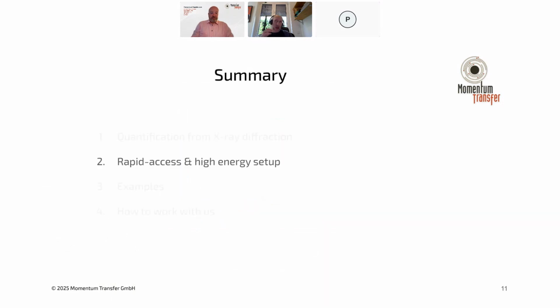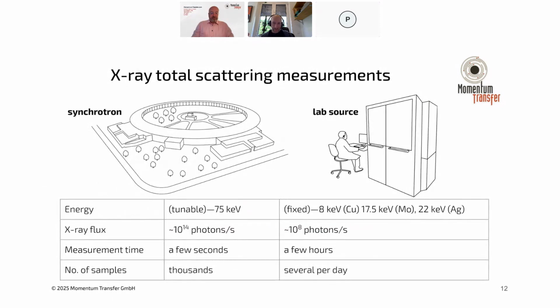Okay, and so how do we do this? How is it typically done? It's typically done with laboratory diffractometers, or in some cases, people have more portable devices that are used in the field. And these lab sources work on essentially metal anode tubes. So typical is copper or cobalt, and for reasons that I'll get into a bit later, sometimes molybdenum or silver or other metals. These anode tubes can generate about 10^8 photons per second in terms of X-ray flux. So this is pretty good, but this technology hasn't changed in about 40 or 50 years. It is basically working the same way that it has been.